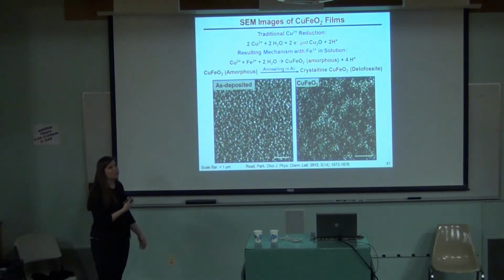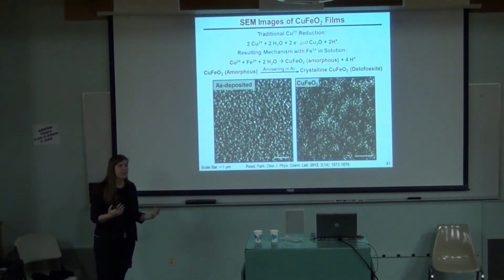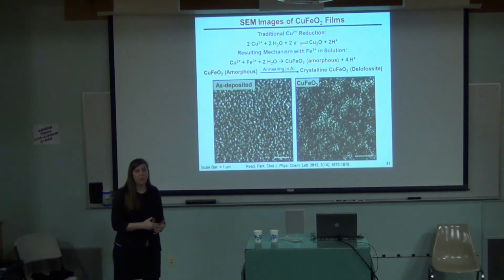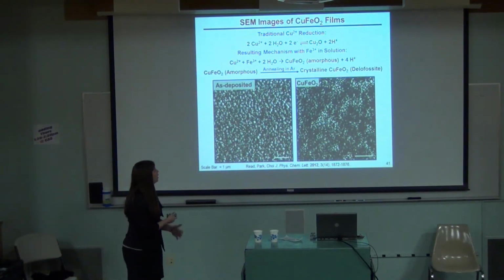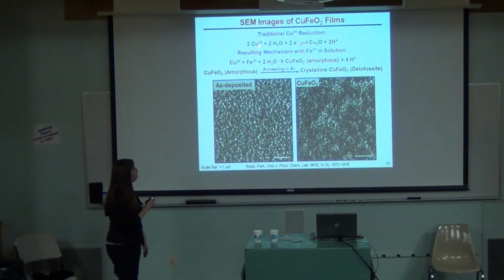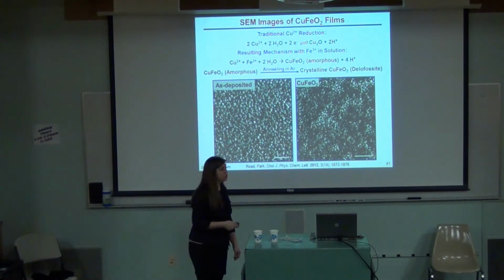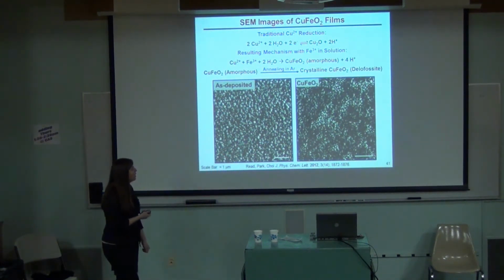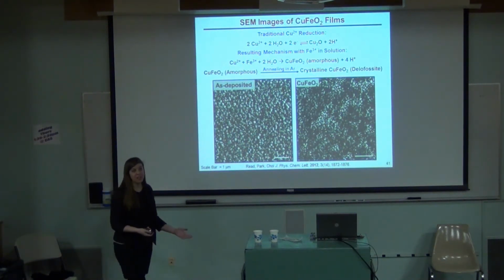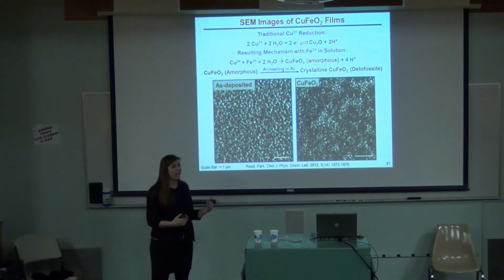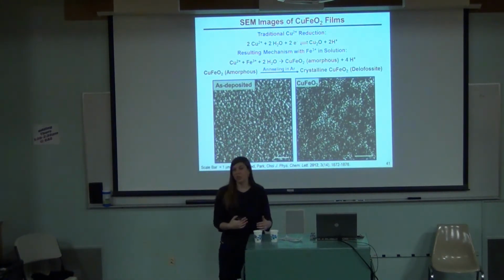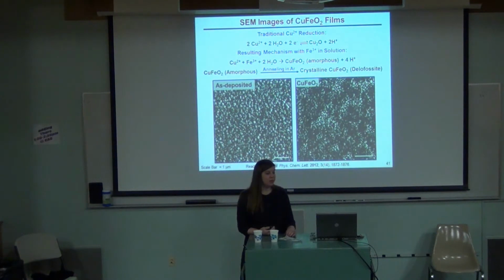So that's what I did, and that was so that the iron would stay in solution, because like I said, they weren't soluble in water. So that's what helped me get them to be in solution so that I could focus on the copper chemistry, because that's what I wanted to focus on to begin with. So when you do that, you can reduce the copper 2+ to 1+, and the iron stays as 3+ because we weren't going to reduce that, and it wasn't enough reducing power for that. And I did get amorphous Delafossite, so that was a big deal. I actually deposited a Delafossite structure, it just wasn't quite crystalline, and with a slight annealing, I was able to keep it in that Delafossite structure and make it a crystalline material.